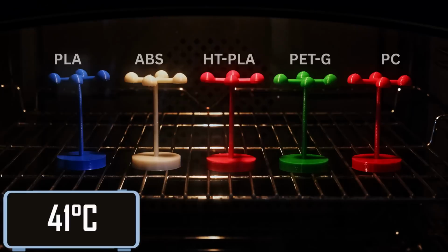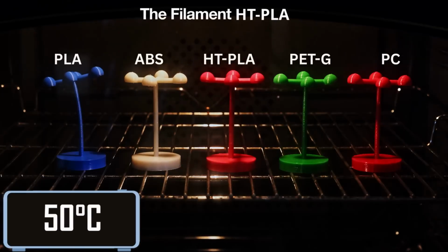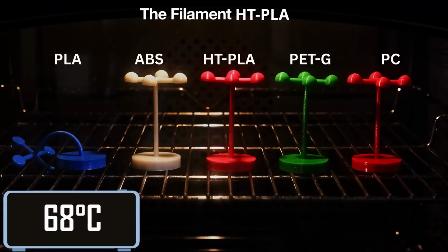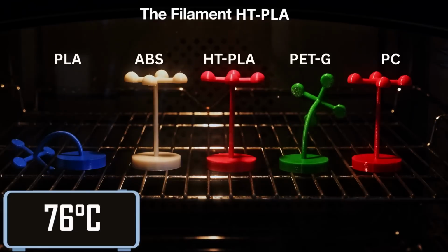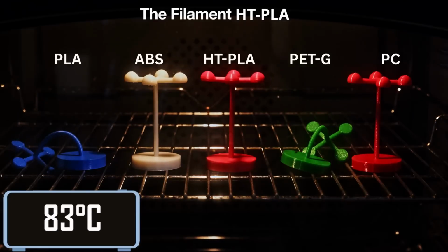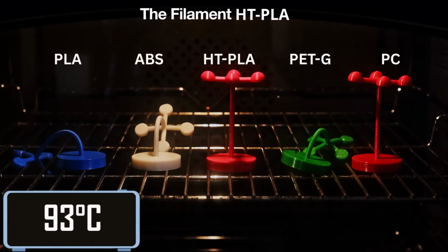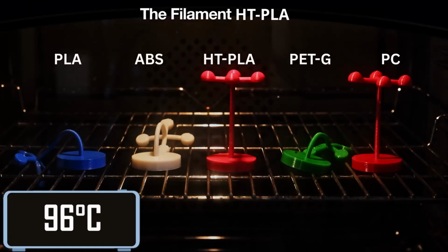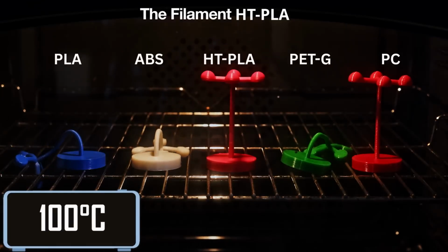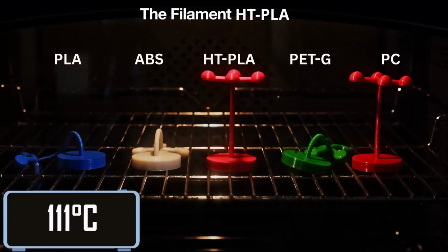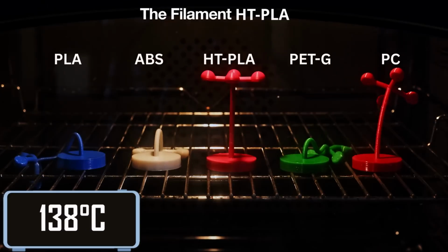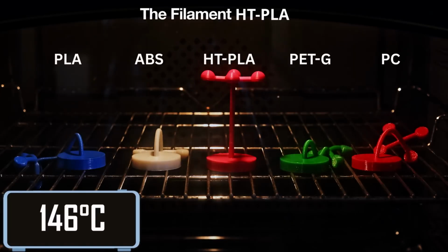And here we are in the oven with our 5 filaments: PLA, PETG, ABS, PC, and of course HT-PLA. At 50 degrees Celsius we have PLA going down, followed by PETG at 75 degrees, and then ABS at 95 degrees, followed by PC at a whopping 140 degrees. But still standing and holding its shape, we have our new HT-PLA.